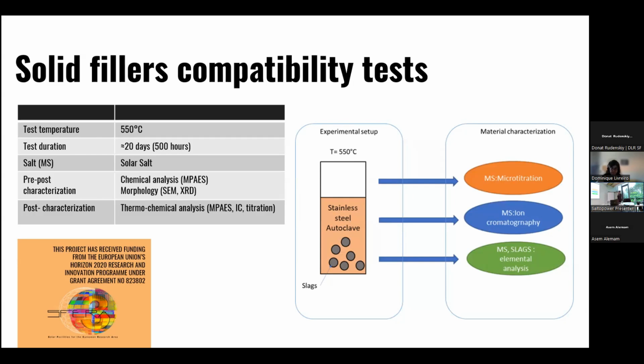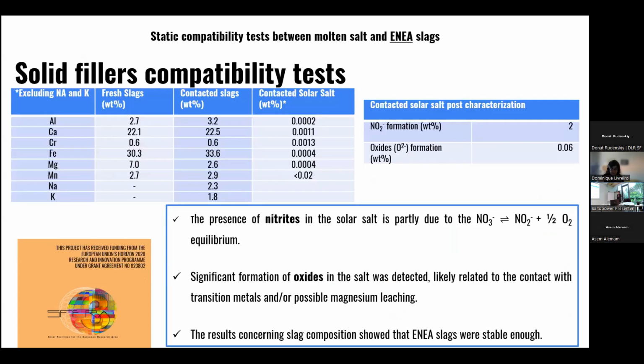After all the tests, we characterized all the materials. That means that we characterized the salt before and after the test, and also the slags before and after the test. Here are the techniques: microtitration, ion chromatography, and we performed also elemental analysis on the slags, just to see if they were affected by corrosion or something like this. And only a few highlights regarding the results.